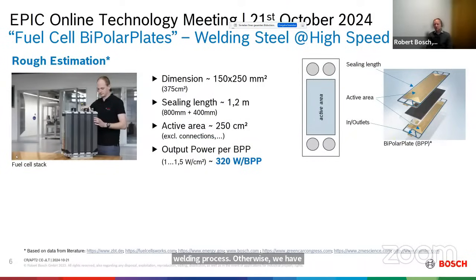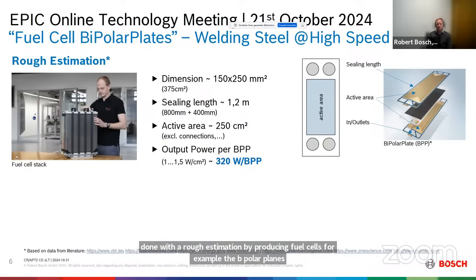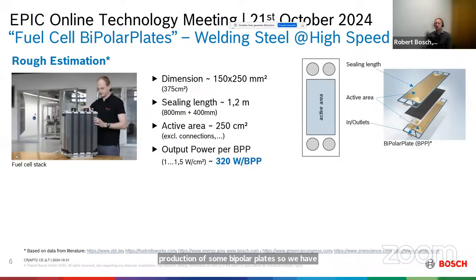And just another simple calculation to show you how important it is to know the process chain, and to consider all the things around the laser. It's a rough estimation for producing fuel cells, for example, the bipolar plates. If we calculate the production of bipolar plates, with, for example, 150 by 250 millimeters per plate, then we end up with a sealing length, so a welding length, if we're using the laser, of 1.2 meters.